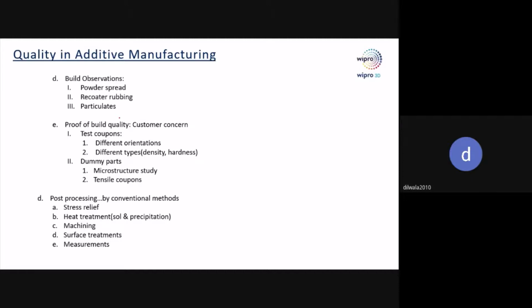So there are a few more customers. They ask, why don't you print dummy parts? Dummy parts in the sense, in the same build, we print a dummy part which is very much similar to the part, but not complete height. From this part, we extract the microstructure coupons and tensile coupons, and then we do testing to see whether the part is getting all the properties in that particular orientation as that of the component. So some customers go to that extent as well for ensuring proof of quality. There cannot be any more questions beyond this. Either you pass or you fail. In most cases, if things are done properly, there is no reason for failing.